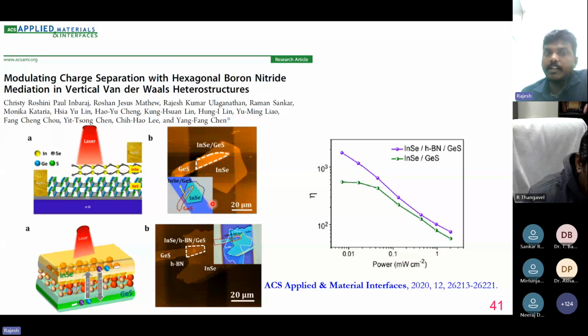In this study, we stacked h-BN, indium selenide and germanium sulfide. Here indium selenide is N type and germanium sulfide is P type. So we created a PN junction device, studied the photoresponsivity and observed a very high responsivity, which is quite higher than the binary indium selenide and germanium sulfide.